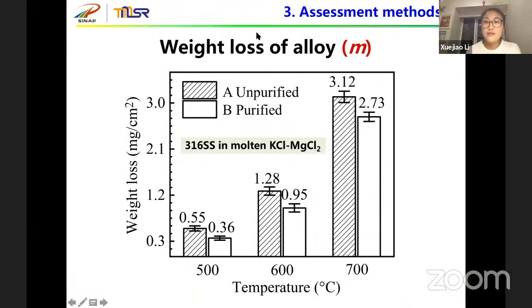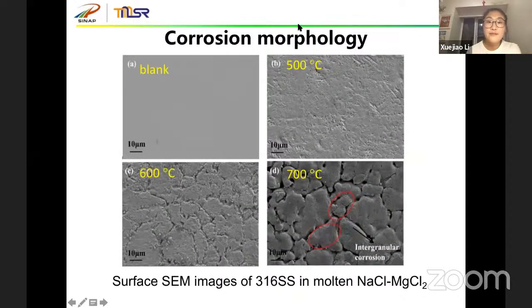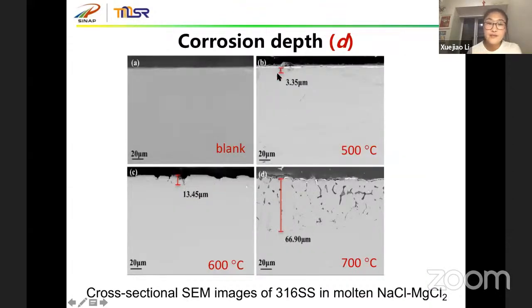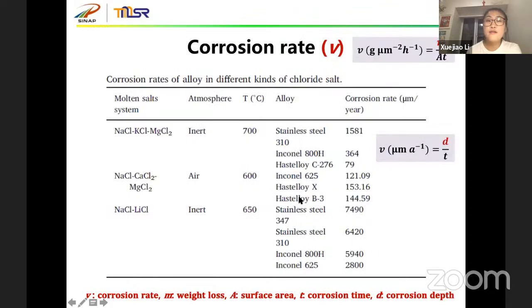Part 3 is the detailed corrosion assessment, including the weight loss of the alloy, the corrosion morphologies at different temperatures, the corrosion depths observed from the cross-sectional SEM images, and the corrosion rate calculated from the weight loss and the corrosion depths.